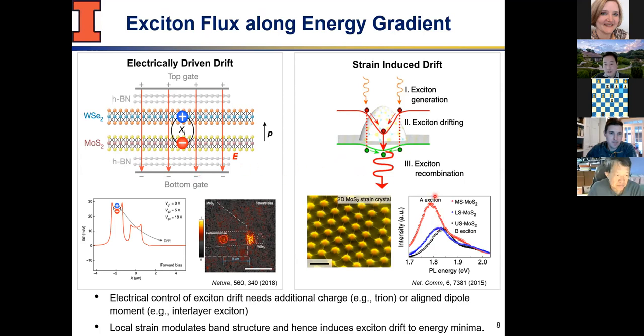And in 2015, that's kind of our interest, another group at Stanford showed that you can use not the electric field, but strain to manipulate excitons. The idea here is that when you apply strain, you start to change the band gap of your semiconductor. And when you change the band gap, the exciton sees a path towards the lower energy of that band gap because of that state induced by strain. So perhaps we can utilize it to do something.